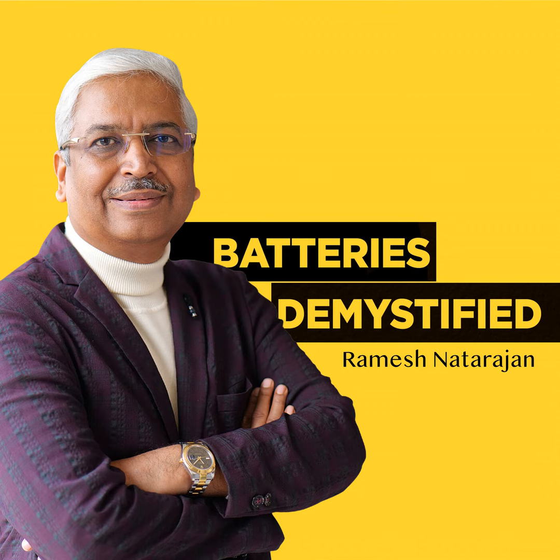The difference is the subtraction of minus 0.20 volts from 2.50 volts. So you have 2.50 minus of minus 0.20, which results in a total voltage of 2.70 volts. Over a period of time, as the cells age, the negative potential does not reverse, resulting in the overall voltage of the cells not exceeding 2.70 volts when charged.